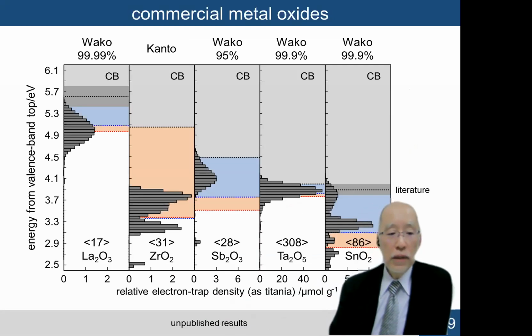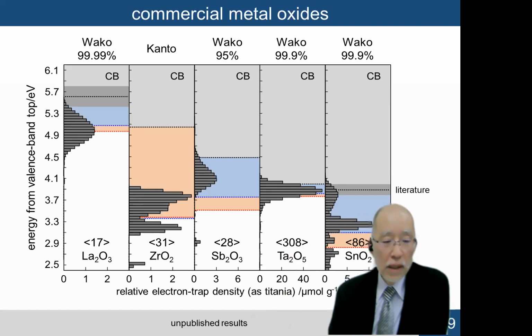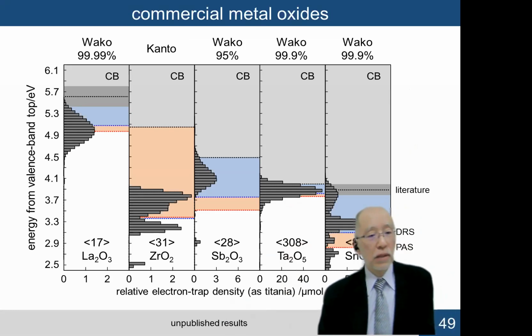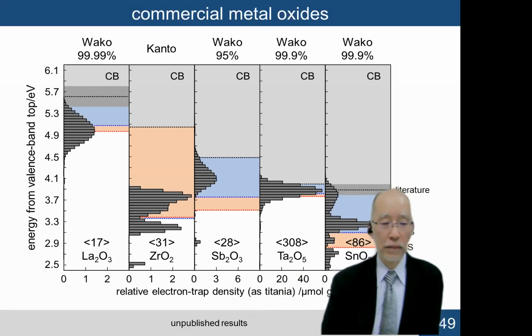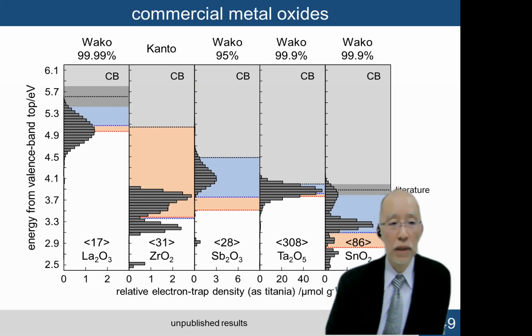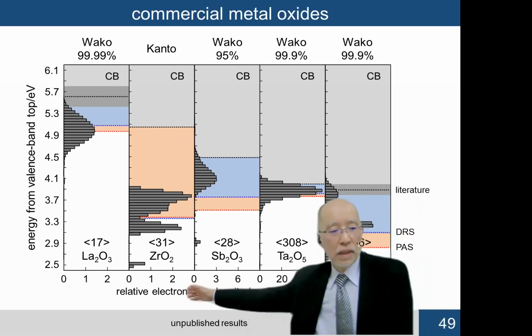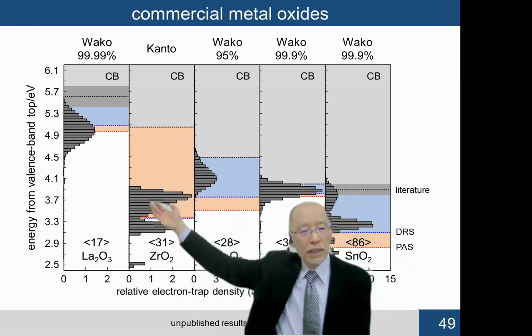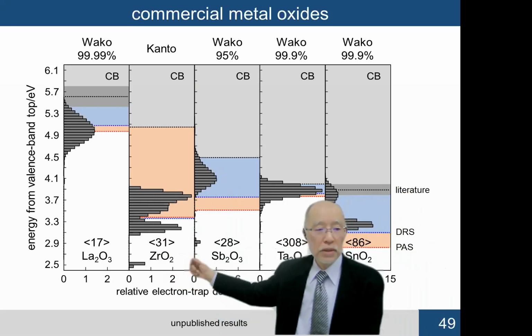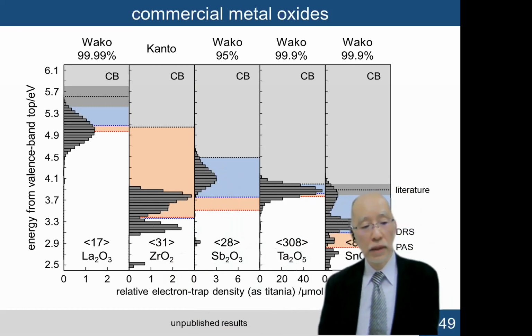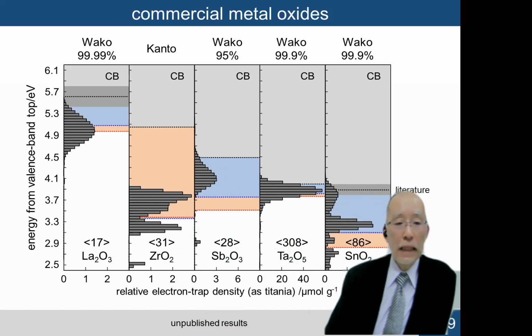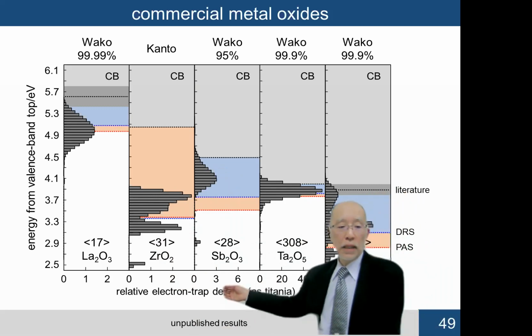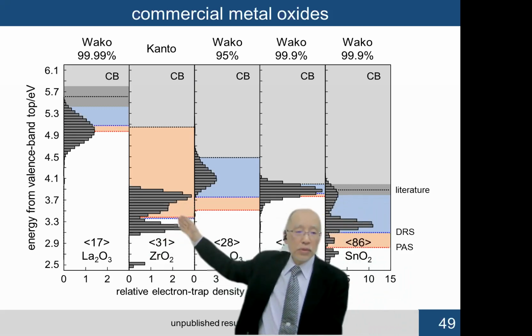For insulators, as I told you, almost all the metal oxides I have shown are N-type semiconducting materials, and some P-type semiconducting materials, for example, nickel oxide, don't give an ERDT/CBB pattern. Probably N-type semiconducting materials can be measured. But insulators, like lanthanum oxide that has a very wide, large band gap, can be detected. And zirconia, silica, and alumina, SiO2, Al2O3, ZrO2, don't give an ERDT pattern if they are pure. But if they are doped or have some impurities, they give those ERDT patterns.